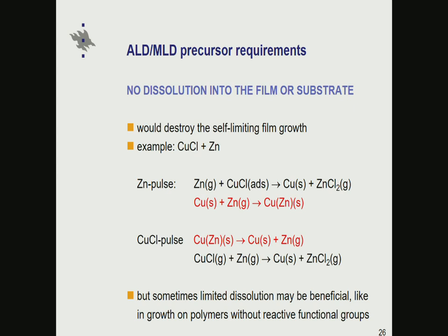On the other hand, sometimes this dissolution into the film or substrate may be crucial to get the film growth started in the first place. For example, when there is a desire to deposit films on polymers which don't have reactive functional groups, the dissolution of one precursor into the polymer may help to get the film growth nucleated on this kind of difficult substrate material. And as Ulla was shortly mentioning, in the case of MLD processes we have lots of possibilities to see this kind of dissolution taking place, especially if depositing porous materials where there is void space where the molecules can go in. Again, something to be kept in mind carefully.